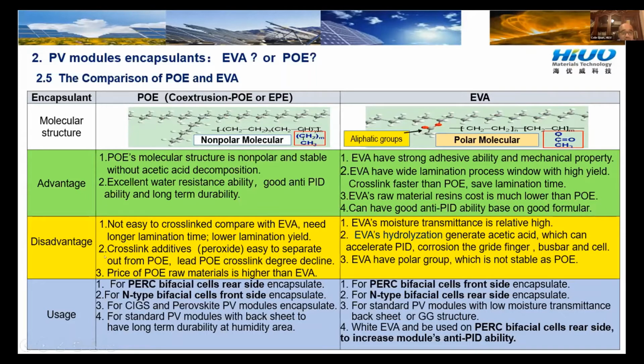Another disadvantage is that the cross-linking additives like peroxide easily separate out from the polyolefin, especially in hot weather and hot conditions. It will separate very quickly, so that will lead to a decline in POE cross-link degree. Maybe some module makers have this kind of experience: if the polyolefin is put into hot weather for about 1-2 months, its cross-link degree will drop, especially for pure POE film.